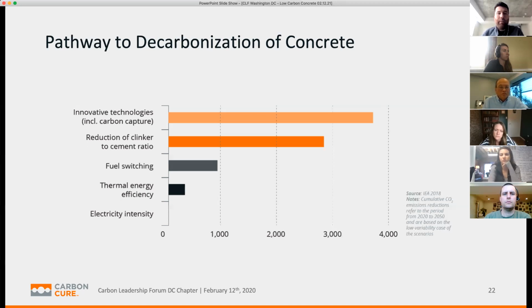And a lot of that comes from the fact that process-based emissions, that manufacturing of cement, makes just a lot of CO2. So what this chart is showing you is that some of the traditional strategies, like energy efficiency or switching of fuels to greener sources, are actually going to accomplish only a minimum amount of carbon reduction. So even if everybody was running on pure wind power, you might get a 15% reduction or so in the carbon impact of concrete. It's really the two strategies at the top that are going to be the most influential.